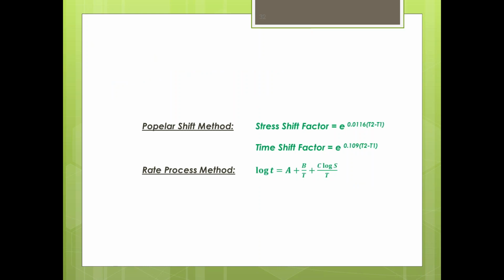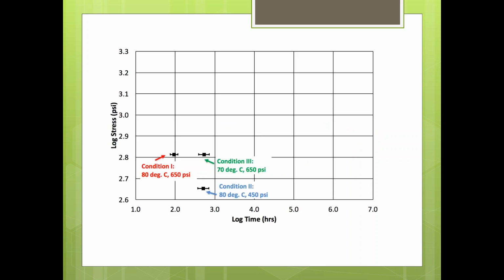The nice thing about thermoplastics is that you can actually have a very good sense of what it's going to act like 75, 100, 200 years from now through really 2 main methods for analyzing long-term performance. The Popelar shift method and the rate process method have been used for a very long time, especially in the gas pipe industry, and the auto industry, and others, to really have a great understanding of what this viscoelastic thermoplastic material is going to act like down the road, given a certain level of stress. So both are very viable options. The methodology that was utilized and really validated the most through empirical data was the Popelar shift method, which you'll see here in a second.